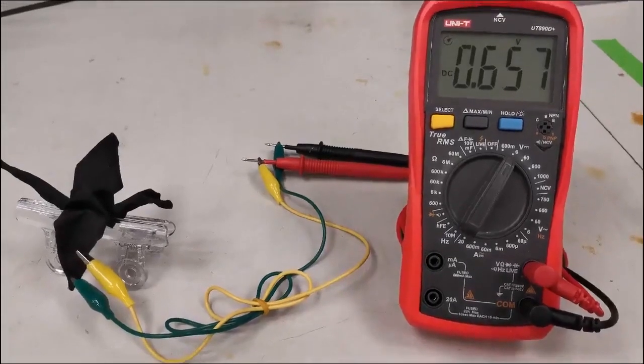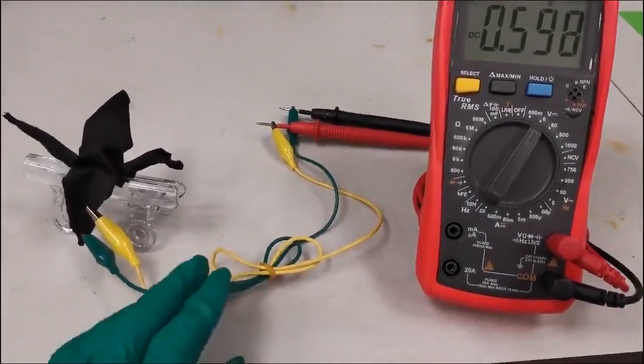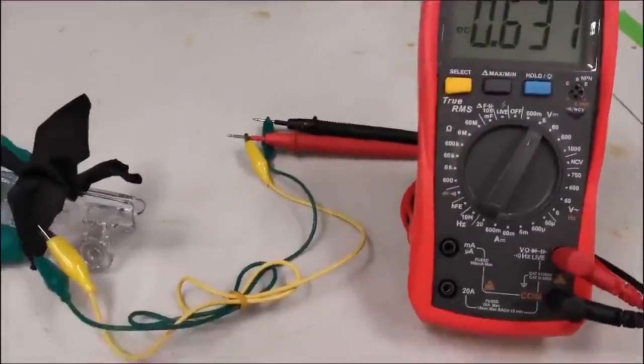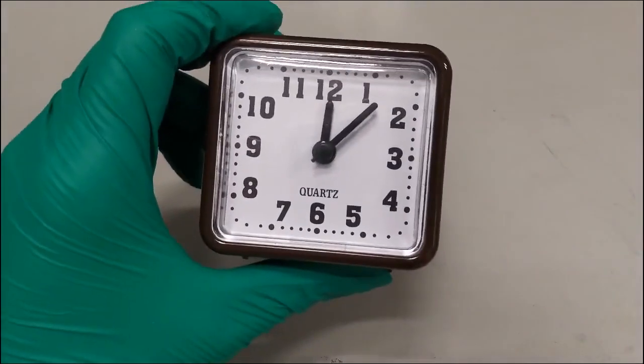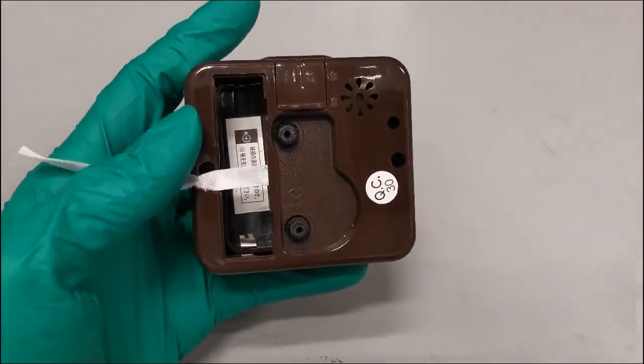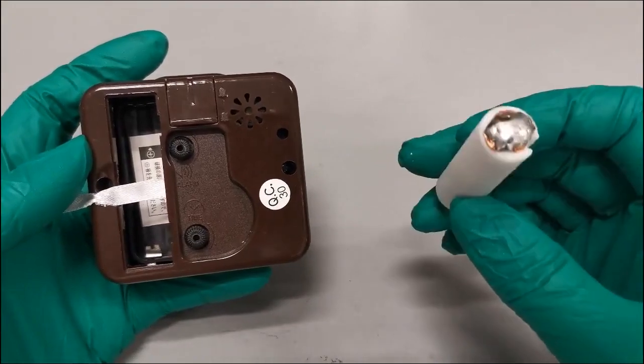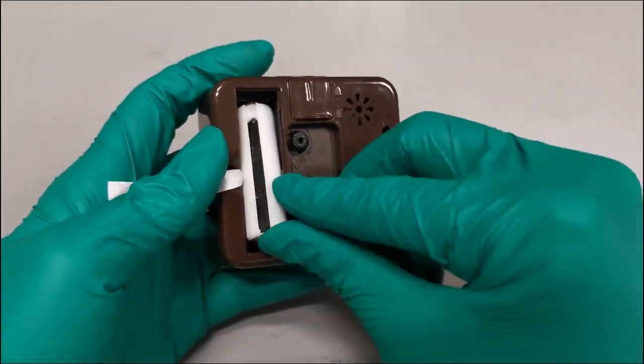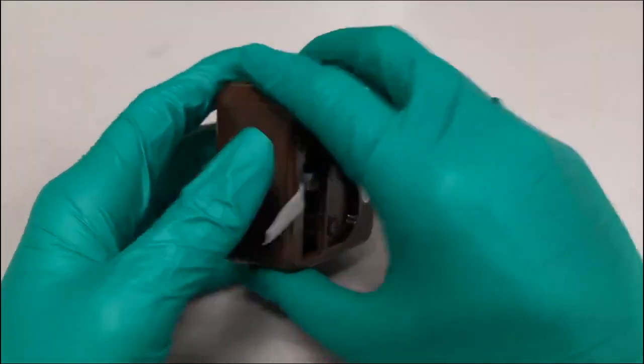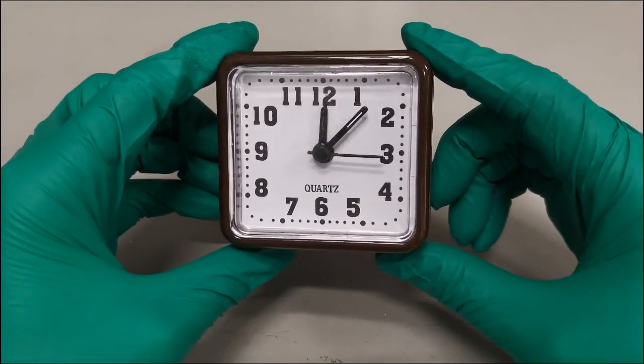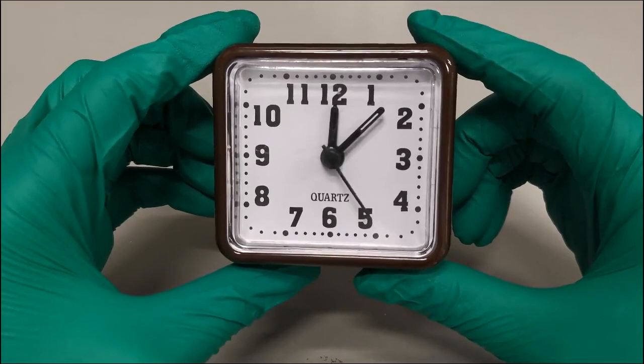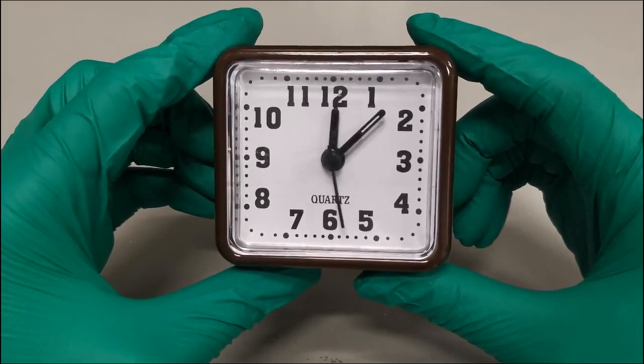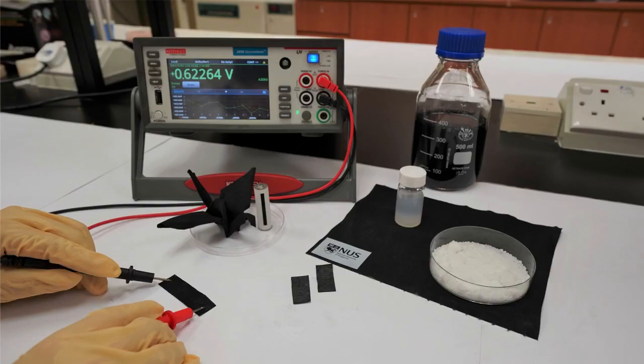The MEG device has immediate applications due to its ease of scalability and commercially available raw materials. One of the most immediate applications is for use as a portable power source for powering mobile electronics directly from ambient humidity. After water absorption, one piece of power generating fabric that is 1.5 by 2 cm in size can provide up to 0.7 volts of electricity for over 150 hours under a constant environment.